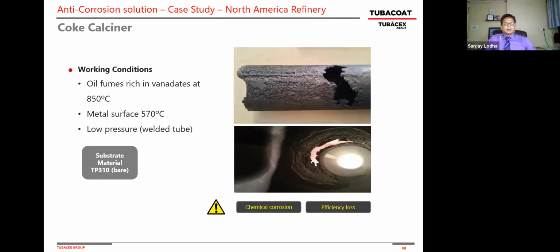Okay, as you can see on the screens, the flue gases in this recuperator heater in the coker calciner are extremely corrosive. I mean, you've got sulfur, you've got vanadiums, and you have a very corrosive environment. Metal surface of 570 degrees Celsius, close to 1000 degrees Fahrenheit. You can see the tubes basically can't survive this environment, and that causes chemical corrosion due to these vanadiums and sulfur. They have to plug the tubes, and that's a huge efficiency loss and operation cost, and then they have to reduce the throughput in a coker calciner.